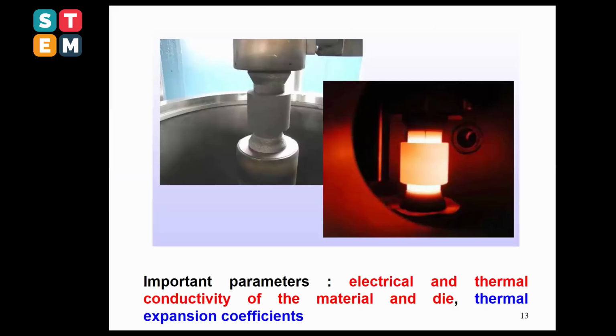Basically, here you have the mold inside the chamber. These are both electrodes, where you also have some cooling water, and during the heating you can clearly observe here. But the main parameter here is to take care about the electrical and thermal conductivity of materials and die. The idea here is to avoid the thermal expansion coefficient mismatch.